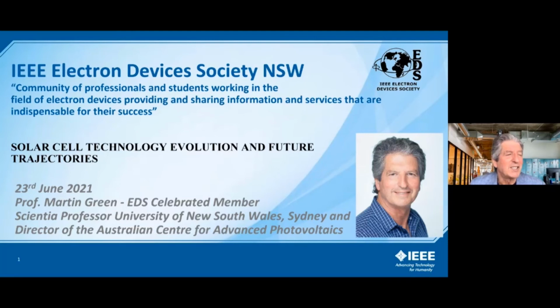Yes, it's tending to increase. With these bifacial modules, you need to have a transparent backsheet rather than the opaque, highly reflective one that's commonly used. You need one that's non-reflective, essentially, and transparent. So, obviously a good candidate for that is glass. You can get transparent polymeric backsheets, but glass is a good candidate. That helps seal out moisture from the module. And most module suppliers that are supplying glass modules will now give you a 30-year warranty.